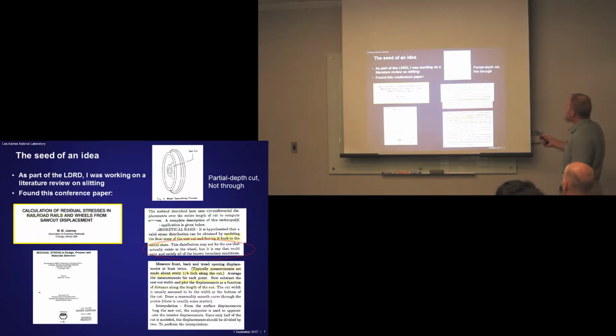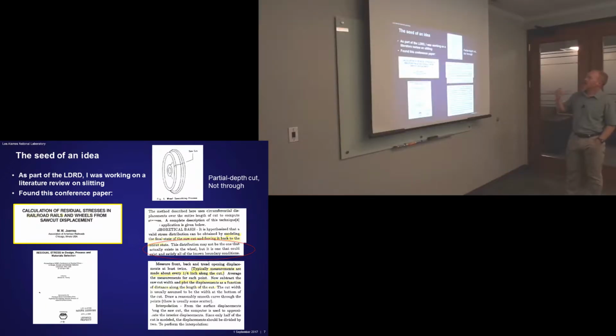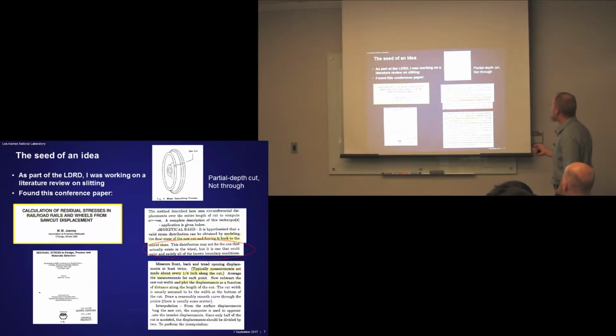And what he did was, here's the wheel. Actually, the measurement was on a wheel. Did a saw cut from the outside radius in, so that's the edge of that saw cut. And he had made marks on the inner and outside, this front surface and then the back surface of the wheel, made some little marks, measured how far apart they were, cut partway through the wheel, and measured how far they moved. And then he took those readings, interpolated them a little bit, and did a finite element model and forced it back flat. And he says here, it might be right, but he's not sure if that's the right answer.